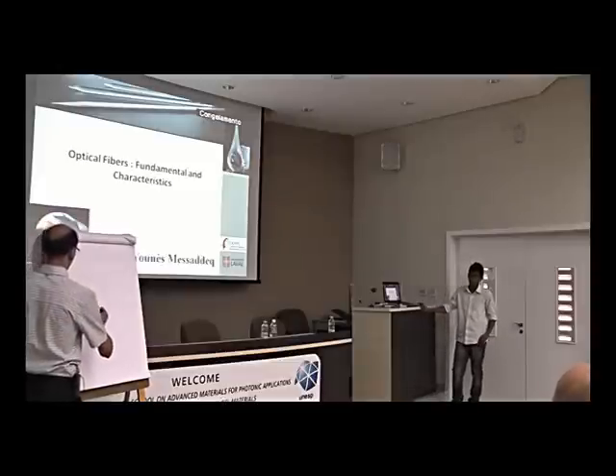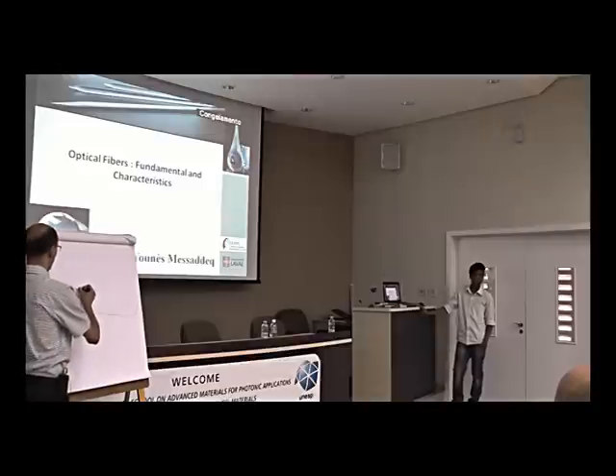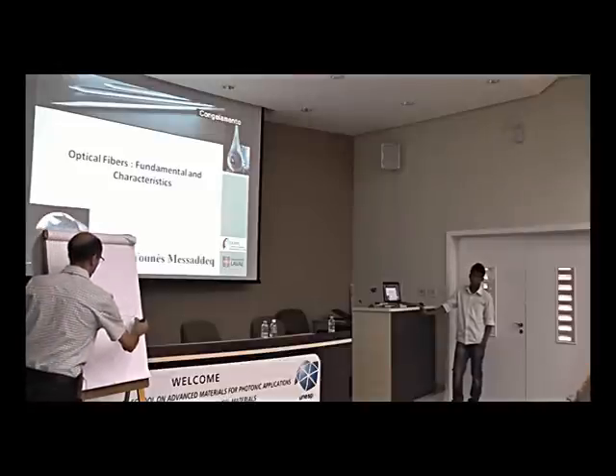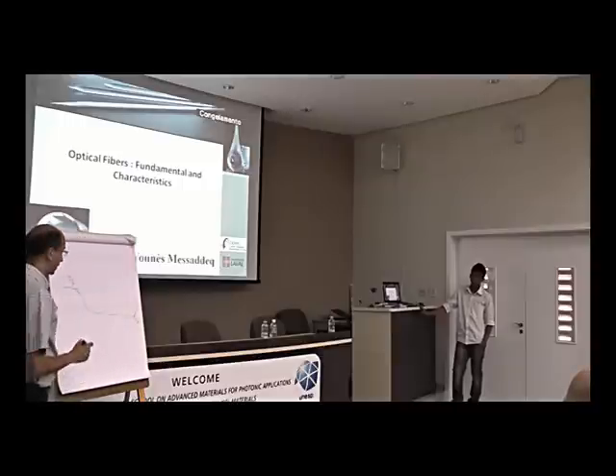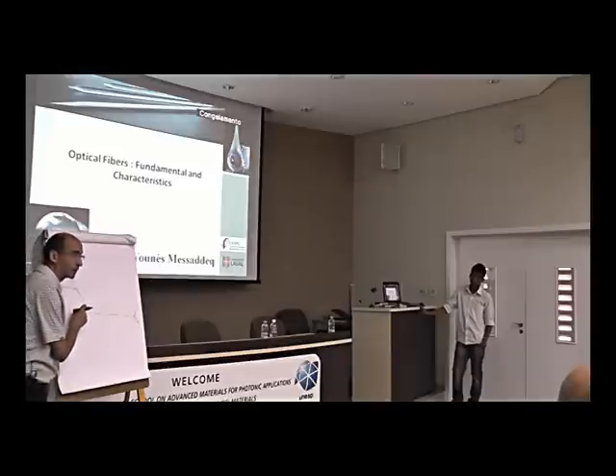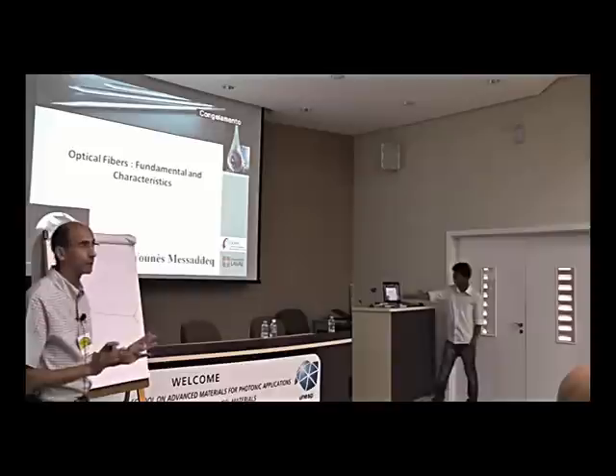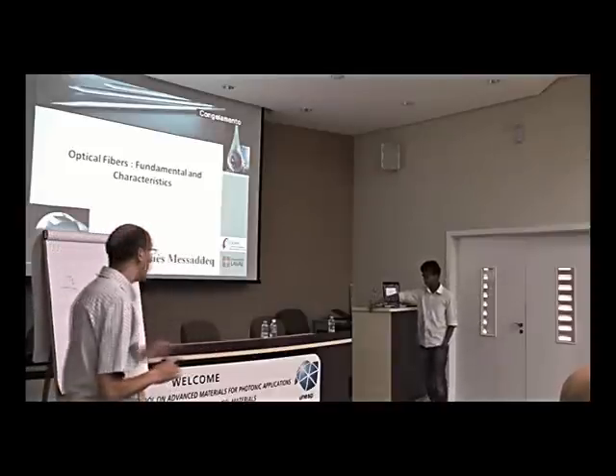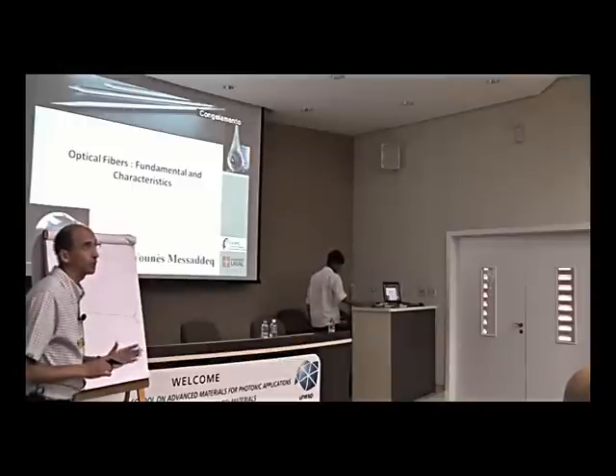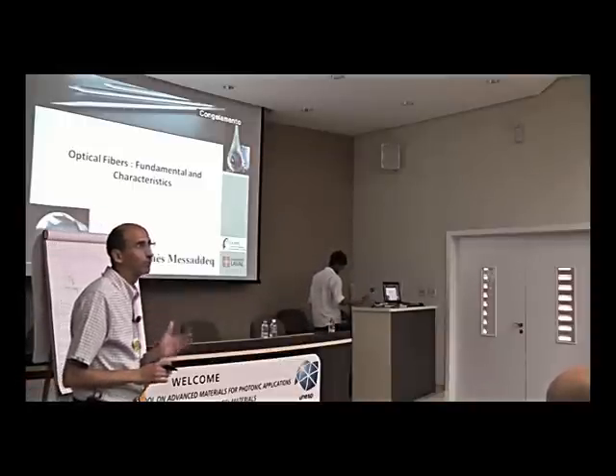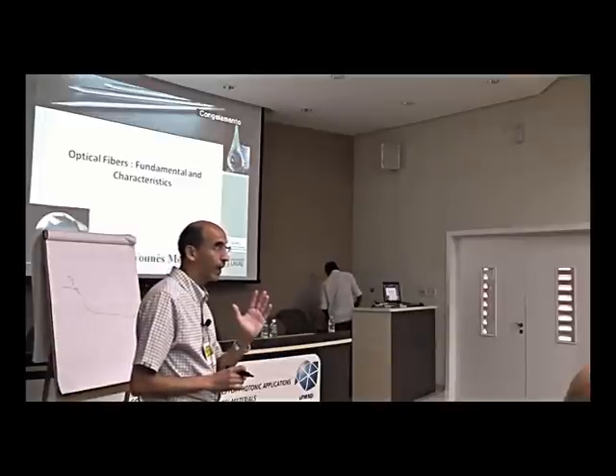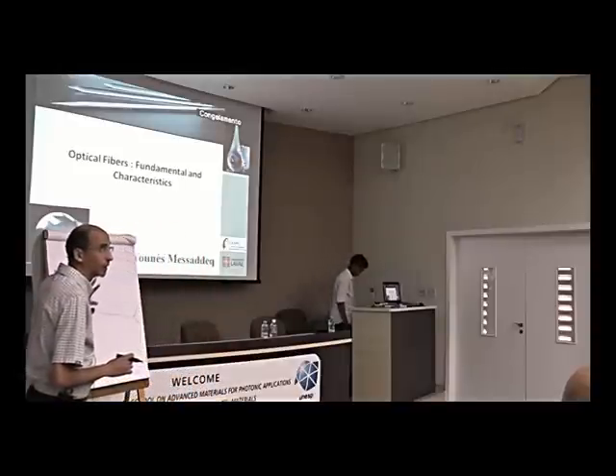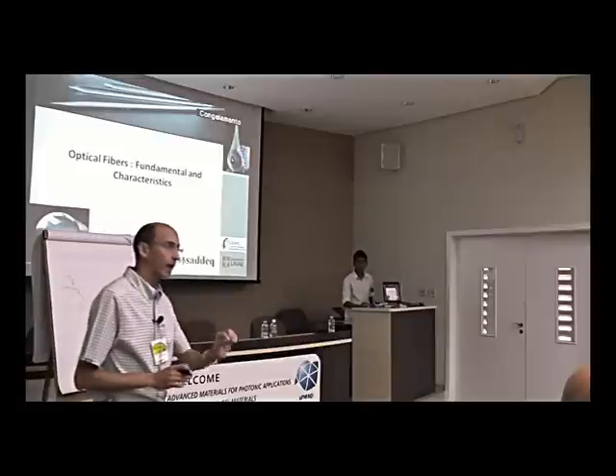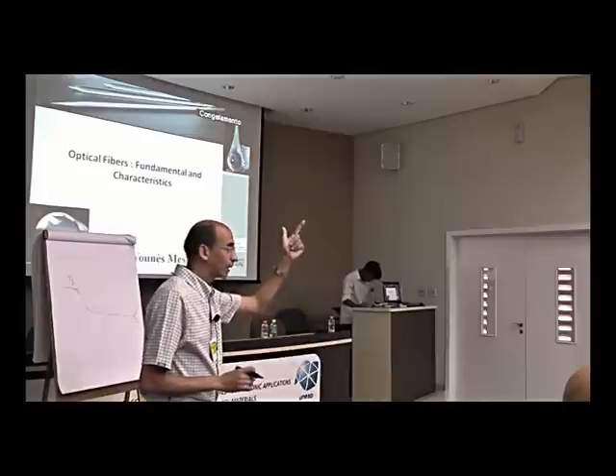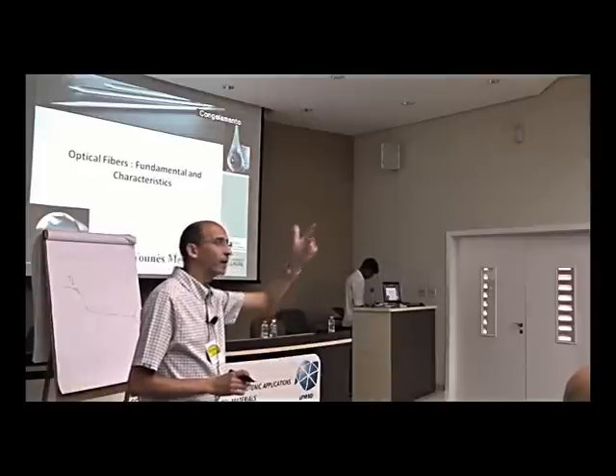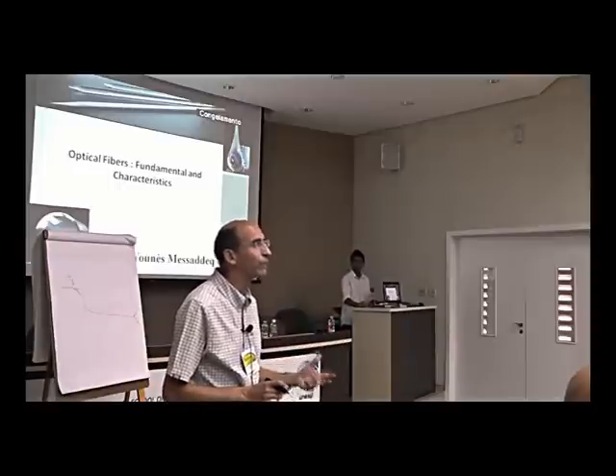Let's just take this, this is the Tg. And here we have the onset of crystallization. Here, never will you find the softening temperature. Using the DSC curve, never will you see it. This is what I told you. We need all the time to make the viscosity measurement of your glass. Without that, you can't know it. Never does the DSC curve give us anything but the characteristic temperatures of the glass. What are the characteristic temperatures? Tg, crystallization and melting, or any other event, oxidation or reduction process. The softening temperature you will never get.